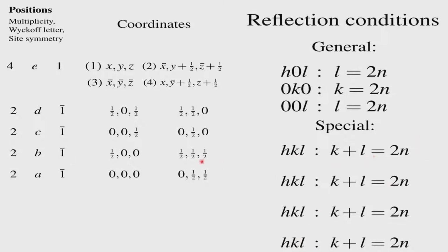These will come only if the atoms are in these positions, but we are dealing with molecules, we are dealing with compounds, we are dealing with complexes. So in such situations we will straight away get these. So only if there is an atom which crystallizes in the space group P2₁/c and is sitting at 0 0 0, you will get this systematic absence.